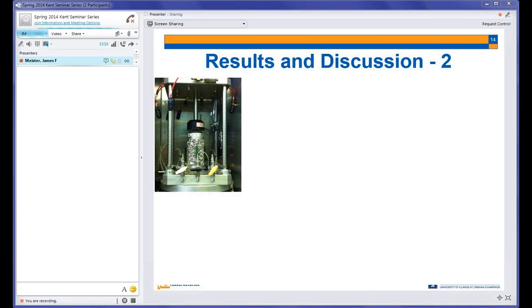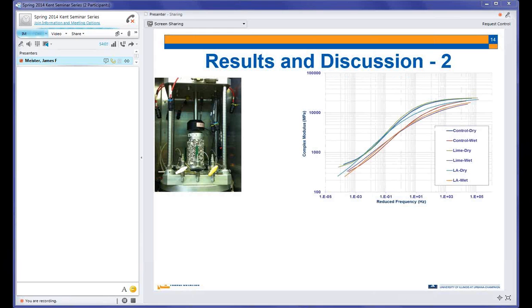So this is the fixture for the dynamic modulus. I'm sure that most of you are aware of it. And these are the master curves, and we have 6 master curves, 3 for the unconditioned and 3 for the conditioned, because we have three mixes. Looking at only the unconditioned states, we can find that the lime and the control are very close to each other. But since liquid anti-strip, as mentioned, softens the mix, it came below them. So the complex modulus of the mix with liquid anti-strip is lower.